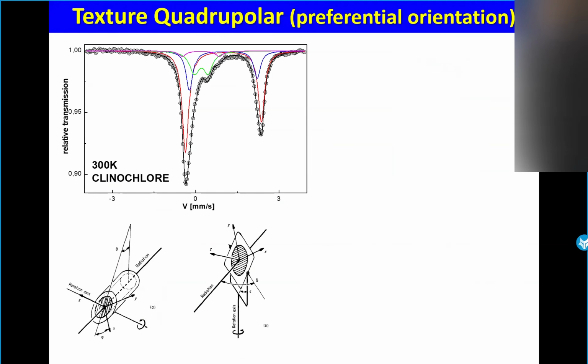So as I mentioned this morning, we can see sometimes in the doublet that the intensities of lines are different. So of course, it was a sample of clinochlore, so for geologists. At the beginning, the temptation is to put only doublets with same intensities. But if you fit the spectrum perfectly, you will obtain some components whose isomer shift has no physical meaning.